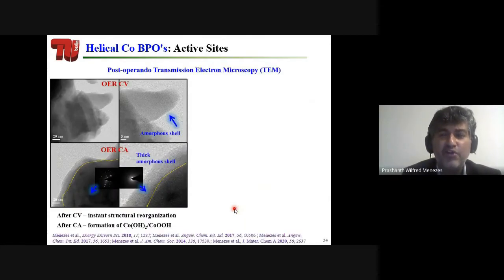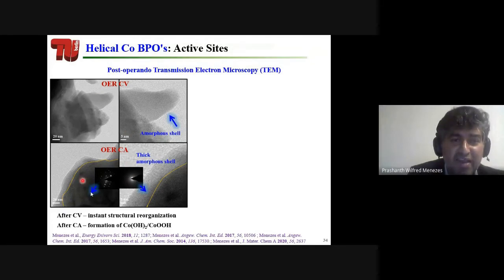So as I said, we are also interested to know what exactly happens to the catalyst. As I said, you take the helical borophosphate or any catalyst for that matter, but at the end of the day, what you are getting is something completely different. This is not going against the definition of a real ideal catalyst. When we looked at the transmission electron microscopy, this is the transmission electron microscopy picture, and you see that we have amorphous and crystalline core shell structure on the surface of the catalyst.